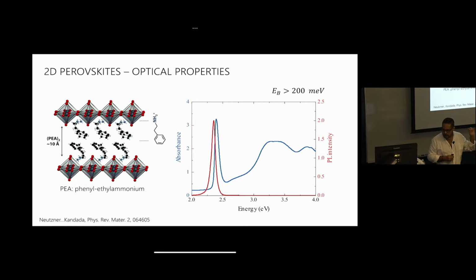The reason that's interesting is that these materials are, in this way, very analogous to classic composite semiconductor quantum-confined structures like quantum wells. But the systems, of course, are optically very different. If you take bulk lead iodide perovskite derivatives and measure the frequency-dependent permittivity, you find a difference between the static limit and the high-frequency limit of something like 100 or a few hundred, whereas in gallium arsenide it's a factor of 10 or so, maybe a few tens. This tells you it's an ionic crystal, a very highly dynamic system.